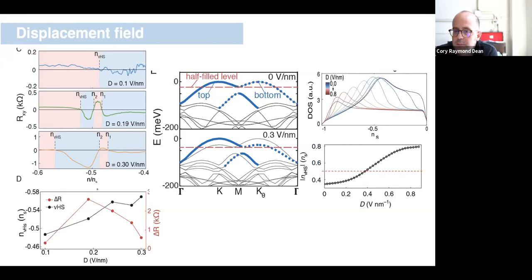And in this system, we actually know rather well from a single particle picture how the Van Hove singularity position evolves with displacement field. And we think, based on the Hall resistance measurements that I identified a moment ago, that we can experimentally measure where the Van Hove singularity is as a function of displacement field, and we can correlate these two results. So what I'm showing here basically is the experimental data point in black, tracking again the Van Hove position as a function of displacement field.